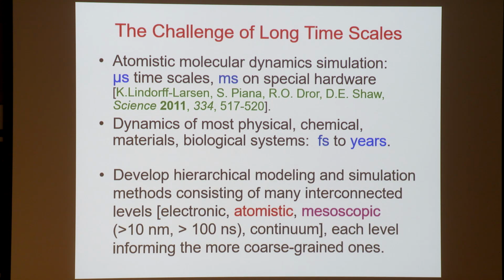We develop hierarchical modeling and simulation methods, which consist of many interconnected levels, from the electronic to the atomistic to the mesoscopic to the continuum, each level informing the more coarse-grained ones, such that we can ultimately bridge what happens at the electronic level to macroscopic properties with a minimum of adjustable parameters. Here we will talk primarily about atomistic and mesoscopic modeling, the boundary between the two being set rather arbitrarily at 10 nanometers and 100 nanoseconds.